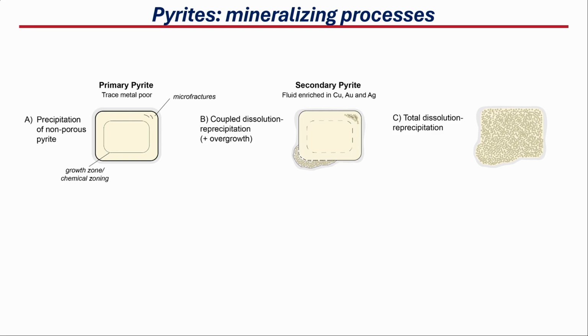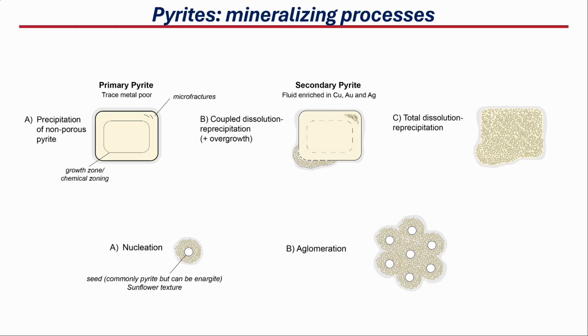So just by looking at different thin sections and different rocks, we actually see that that pattern has also been seen in some of the framboidal-like pyrites. And what we think is that if we have a seed, which can be any crystal of pyrite, and we have even seen it in enargite, we have nucleation of this porous pyrite. In a later stage, we can actually see agglomeration of those framboids, and that's how we get what is called a framboidal-like colony.